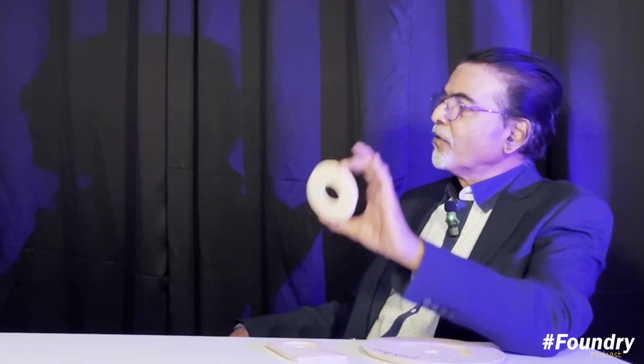In fact, there is a thumb rule for breaker cores. The thickness of the breaker core should not be more than 1/10 of the riser size. Ours is 1/20th. So that is why I can always guarantee that it breaks off at that portion. It not only breaks, it improves the feeding efficiency of the riser.